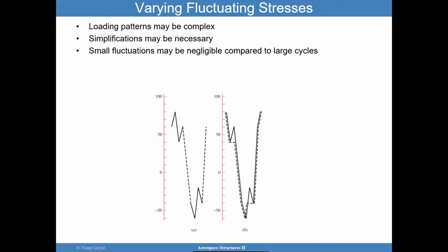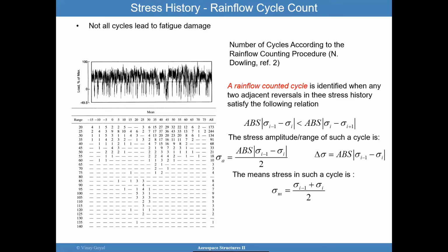So when I look at A here, I have this loading situation where this stress is fluctuating to some level, and you can see this has been plotted here. Now, one could consider this particular increase and drop is potentially not significant to the fatigue life. You could say that about this little peak here. So one approach is to just truncate that and simplify what you really consider a cycle. And so not all cycles really lead to fatigue damage.